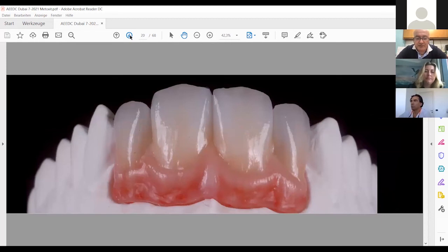This is the final quality of the surface. What's important? We don't want to see something that is really opaque, or a patch where you can see there is no color inside. That's important because in the oral cavity, the quality of the material is important for longevity. It's important for leakage of the bacteria that can build up on top of this surface. So the quality of the micro grain size of the material allows you to make a very smooth surface. Next.